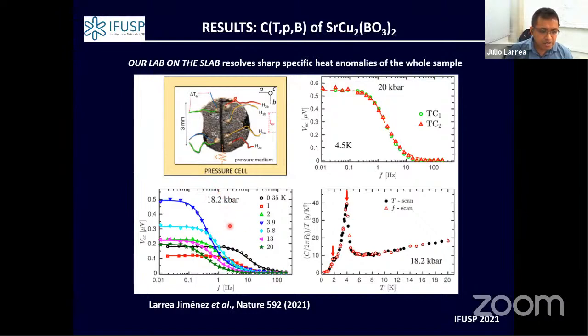When we apply pressure and do the frequency scan measurement, what we can resolve is a very sharp peak in the specific heat. If we select the frequency where the specific heat maximizes, we fix that frequency and then make a temperature scan.